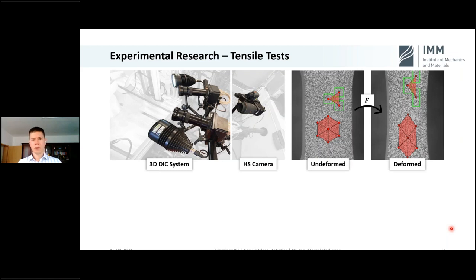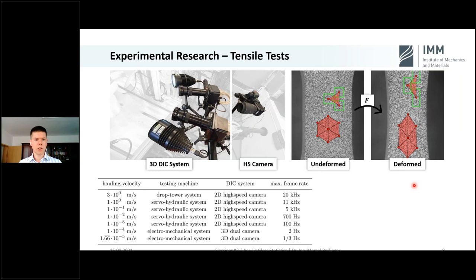Strain is measured on the surface of the specimen. Therefore, a stochastic grayish pattern is brought into the surface. And because it is so chaotic, no point matches the other on the surface. And so we can track single points from one picture to the other. And doing so, I had sets of 7 velocities I tested with different testing machines, different material testing machines.